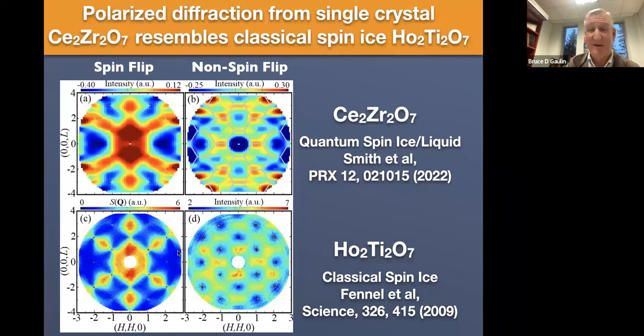One of the reasons is that this was one of the experiments that really put classical spin ice on the map. This is quite a famous experiment by Tom Fennell and co-workers, published about 13 years ago, where he did exactly the same experiment, even on the same instrument, on D7, but on holmium titanate rather than cerium zirconate. And holmium titanate has a magnetic dipole moment of about 10 Bohr magnetons, so it's about 8 times bigger than what we have in cerium zirconate. So the cerium zirconate experiment is frankly quite a bit harder. But nonetheless, there are both interesting similarities and differences.